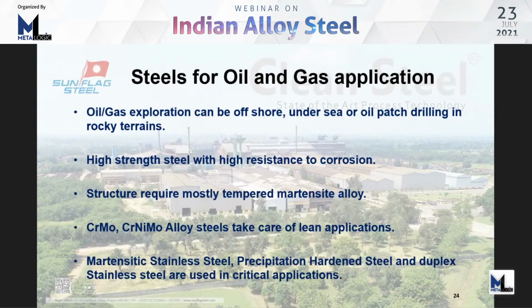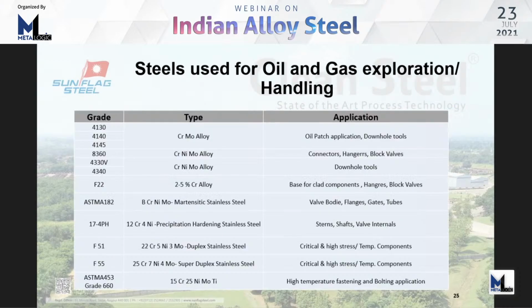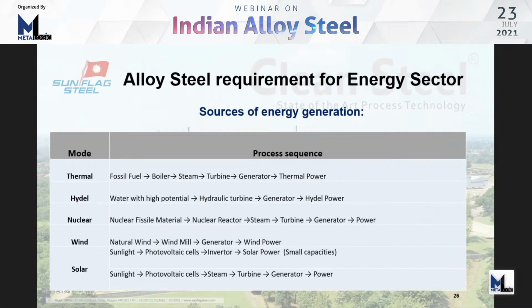For oil and gas, we normally require high strength steel with high resistance to corrosion, and the structure being mostly tempered martensite, and chrome moly or chrome nickel moly alloy steels take care of the lean applications. Whereas for higher end applications, martensitic stainless steels, precipitation hardened stainless steels, and duplex stainless steels take care of the application. In the oil and gas industry, these are some of the applications. The upper ones are the lower end applications, the bottom ones are the higher end applications. You can see that upper ones are mostly low alloy, whereas the lower ends are stainless steels.